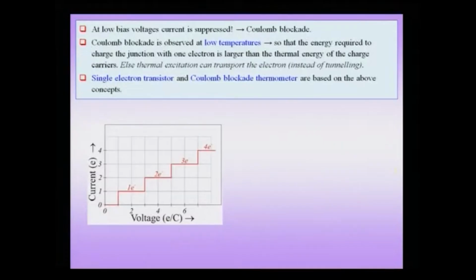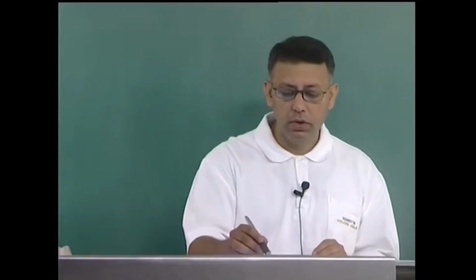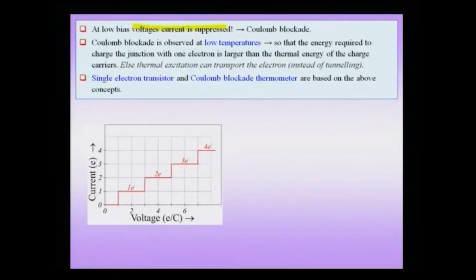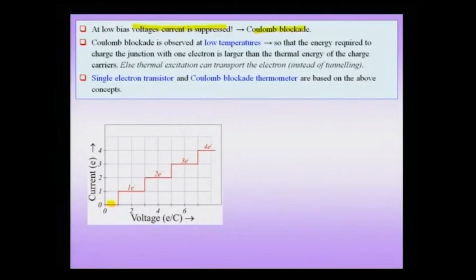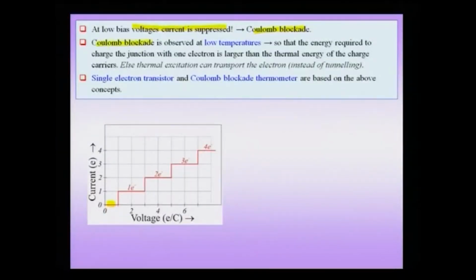At low voltages, first of all, the current itself is suppressed. That means if you have very low voltages, no current passes through the system, and this is called the Coulomb blockade. In a normal conductor, if you have low voltages, you will still have some current, though the current value will be small. Typically, for a Coulomb blockade to be observed, you have to work at low temperatures, because otherwise at higher temperatures thermal excitation can transport the electron instead of tunneling. Purely by thermal excitation this barrier may be broken, and therefore you will have some conduction and will not observe the Coulomb blockade phenomenon.